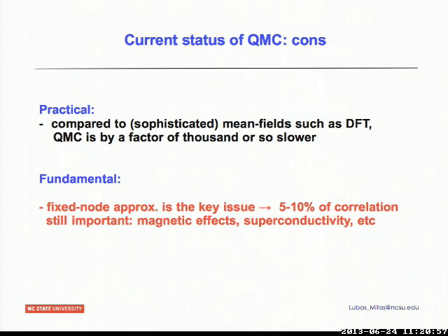And if the fluctuations of the energy are roughly similar or almost the same, you can indirectly claim that the systematic errors you're making are probably of the same type. But it's not a perfect justification. The trouble is that the fluctuations are typically much larger than the energy differences between those states, so you do not have a perfectly clean signal there.